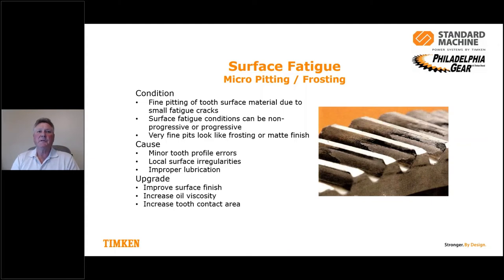These surface fatigue conditions can be non-progressive or progressive. Very fine pits look like frosting or a matte finish. You'll notice that something just doesn't look right on the flank of the gear tooth, and with some closer inspection, you will notice some of these fine pits, and they can look like a matte finish, or like small fatigue cracks. Now, the cause is minor tooth profile errors or local surface irregularity, so the gear tooth is not operating with a good rolling action, or improper lubrication.